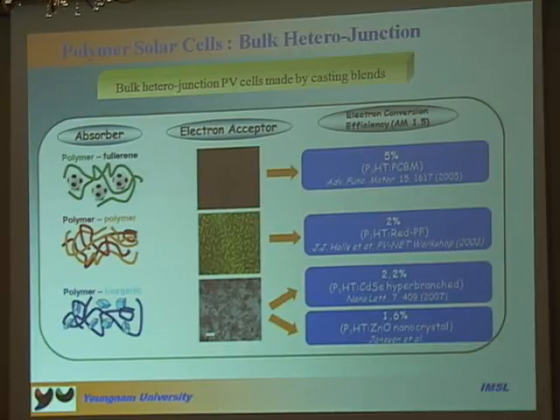In polymer-fullerene, efficiency was 5% by use of P3HT and PCBM, and polymer efficiency was 2% by use of P3HT and Red-PF. And for polymer-inorganic, efficiency was 2.2% with P3HT and cadmium selenide hyperbranched, and 1.6% in the case of P3HT and zinc oxide nanocrystal. In our research, we also use P3HT and cadmium selenide quantum dot.